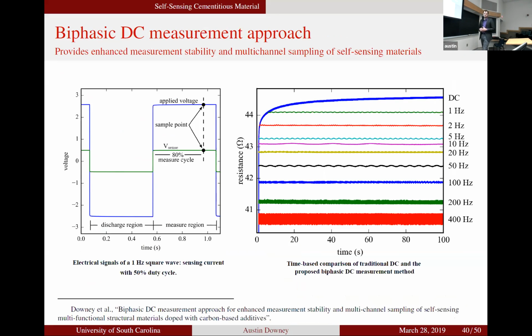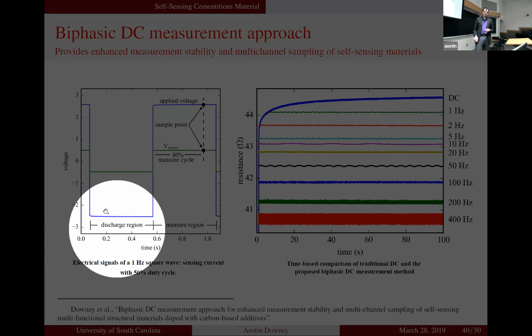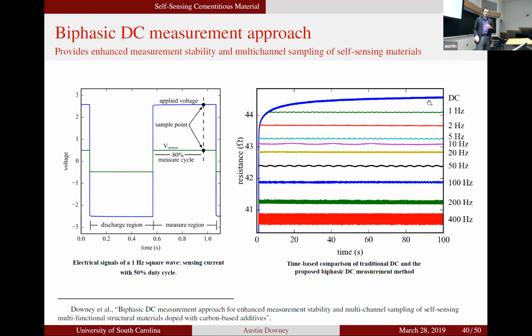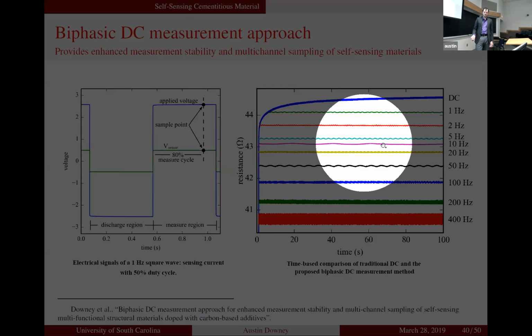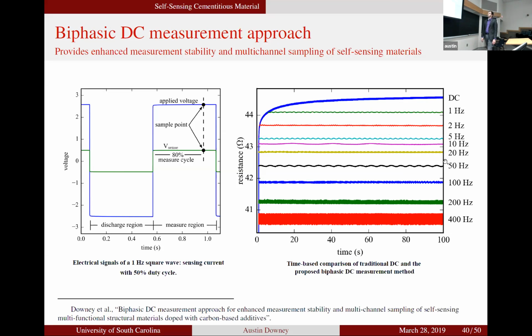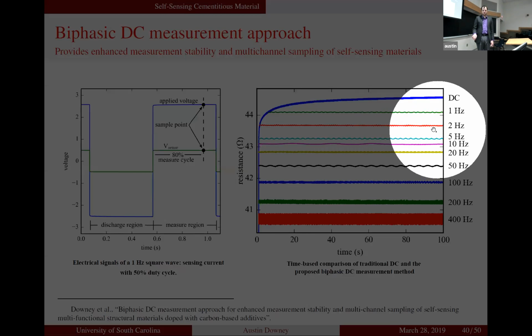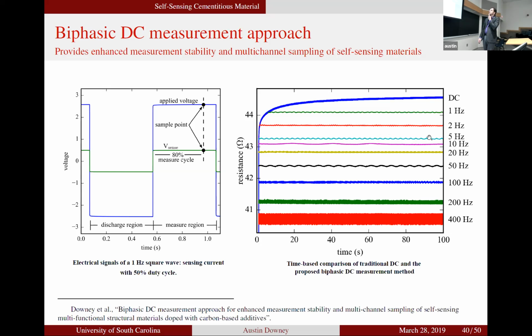So as a simple way to alleviate this issue, we just hooked up a biphasic DC function generator and created a biphasic DC signal, and then developed a measurement approach around that. So we're going to continuously charge and discharge this material, both positive and negative. This blue line here is what you get with a DC approach, right? So it rises up and continues to rise, and then these horizontal lines that are kind of squiggly are the different frequencies of the biphasic approach, right? It doesn't matter what frequency we choose, we get a nice horizontal line, but we get a little bit more noise. So typically we're just going to use a 1 Hertz signal for the remainder of this work, because we're not super worried about the noise. What we want is stability, right?